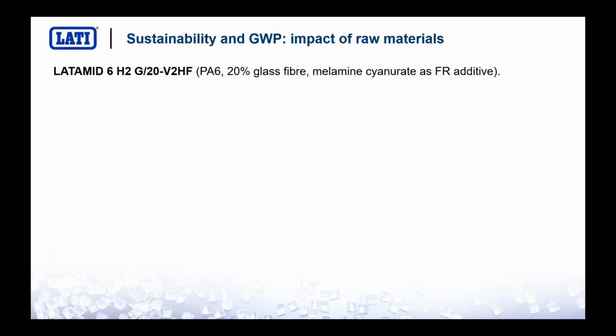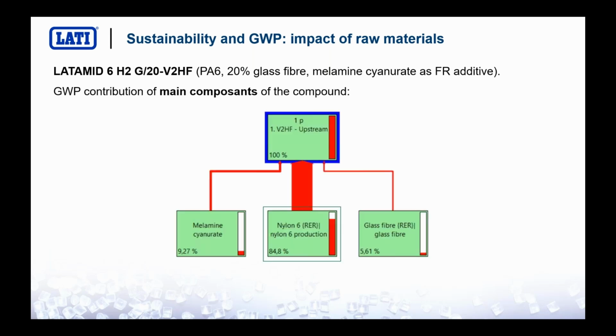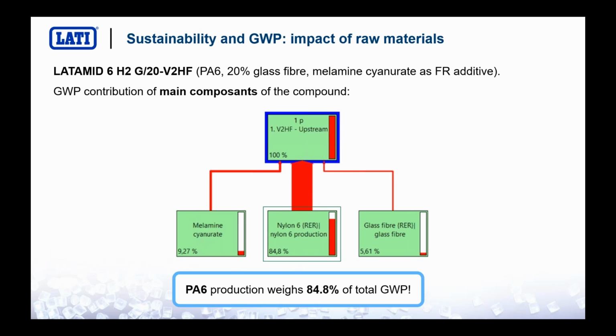Let's try to understand which raw material is actually impacting the most. We have done this exercise on this very material, and what we found is that the main components of the compound do not impact the same way. The biggest impact is due to the production of nylon 6. It's not the glass fibers, it's not the flame retardant system. The global warming potential is coming from the production of the plastic material. The nylon 6 in itself accounts for close to 85% of the total global warming potential.